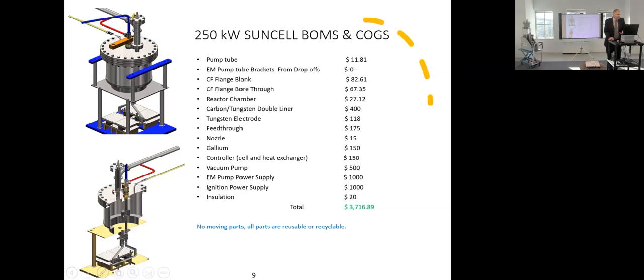And it pumps the molten gallium through this nozzle and shoots it against the counter electrode and completes the circuit. This is a reaction chamber where the plasma is maintained. And then, as I said, we have these refractory materials around it. We use a particular kind of steel. It's very permeable to the Hydrino. That's another aspect. If it doesn't allow the permeation of the Hydrino product out of the reaction chamber, then it won't work. So a lot of technology in this. A lot of innovation went into the SunCell. So this is the different parts, and this adds up to about $3,700 for 250 kilowatt, or about $15 a kilowatt, and has no moving parts, and all the parts are recyclable.